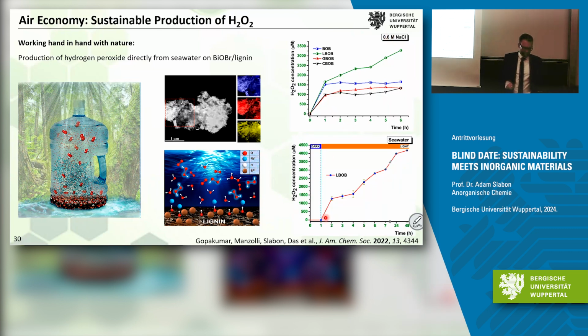So after 1 hour, we start the illumination and we generate the peroxide. We first thought it's coming from the lignin, the oxygen, but we also made labeling experiments with 18-oxygen, and we could confirm that we have the peroxide from the gas coming in. So what I would like to say here is it pays off making green chemistry, because you can outperform pure inorganic materials. Why does it work?